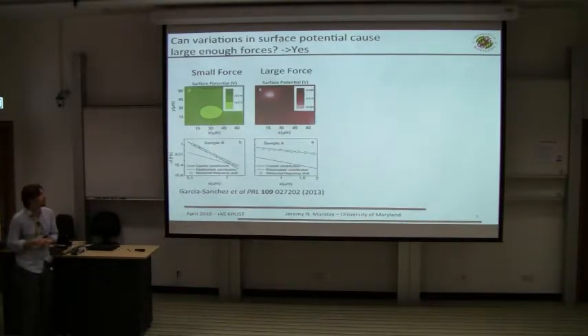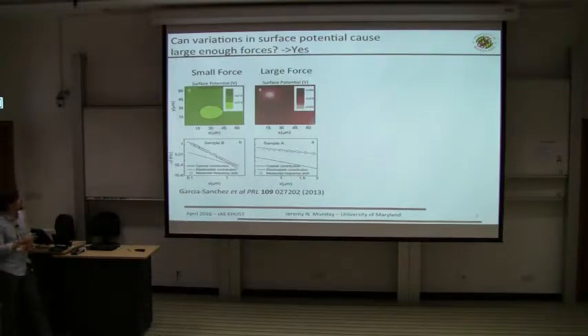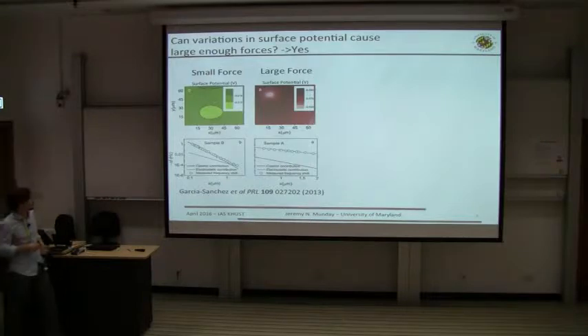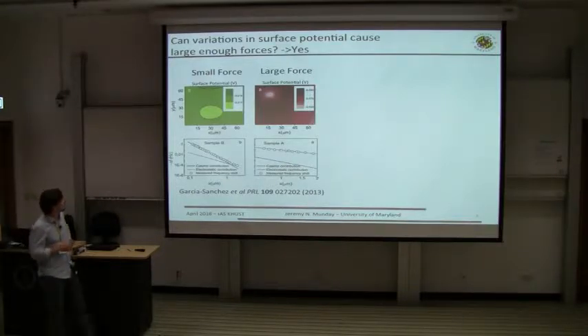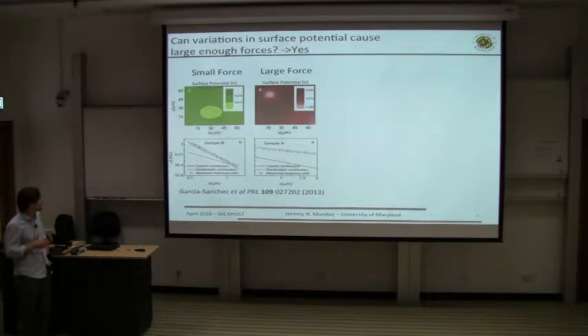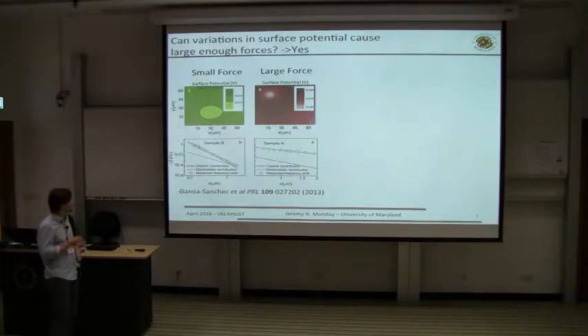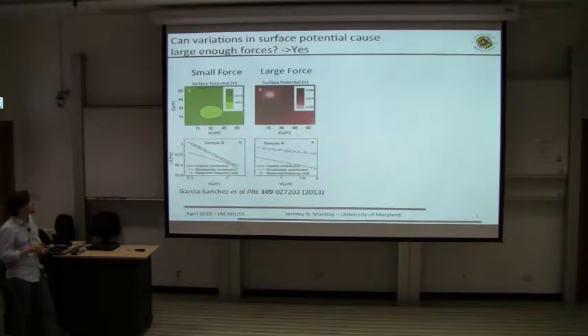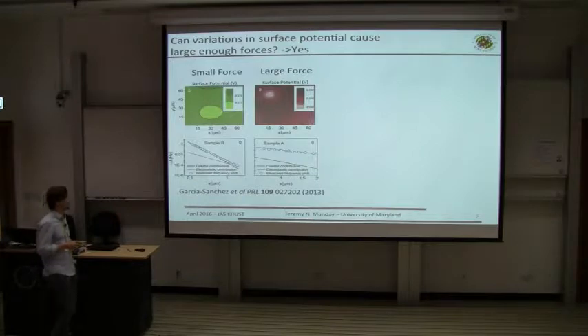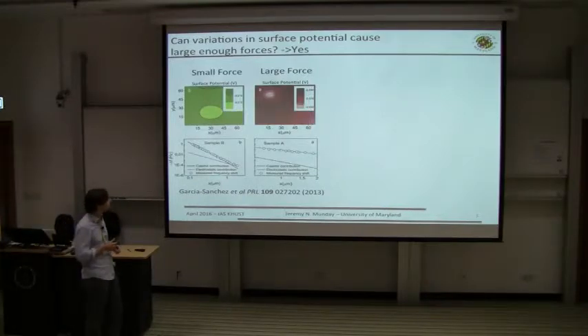Then we can jump forward to some of the more recent experiments that we've seen. This was also mentioned at the beginning. These are the experiments from the Yale group. They were looking at Casimir force measurements between a sphere and a plate, and depending on which types of samples they used, they found that the surface potential across the plate can vary. Sometimes the variation is relatively small, and there's a small force contribution, so you can basically measure the Casimir force and it's not much of an issue. And then on some of the other samples, it actually became an issue, where the measured force was dominated by an electrostatic contribution.